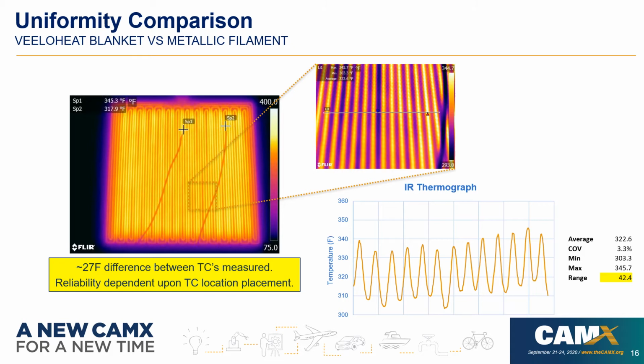Another comparison to conventional metallic filament blankets versus VeeloHEAT Blanket. On this slide, you can very notably ascertain where the filament serpentine design is. Zooming in, you can see those hot filaments, and then the spacing between each filament is really quite cold. So we did an IR analysis here, a line across that image, and we are seeing upwards of 40+ degree temperature variation, depending on if you're on that metallic filament that's heating up, or you're between the metallic filaments.